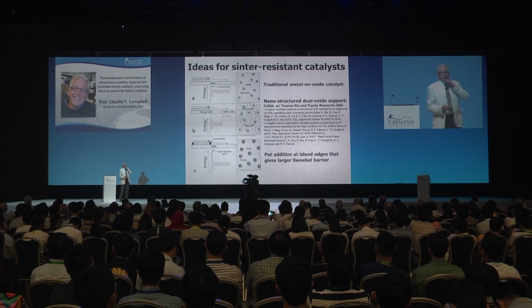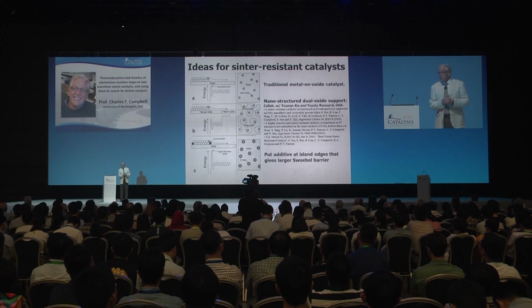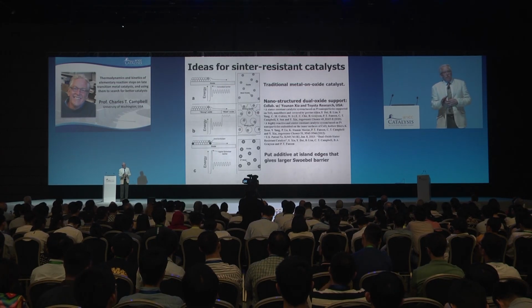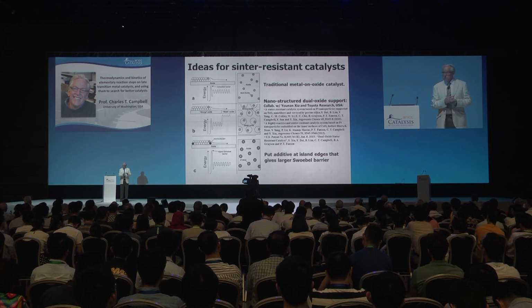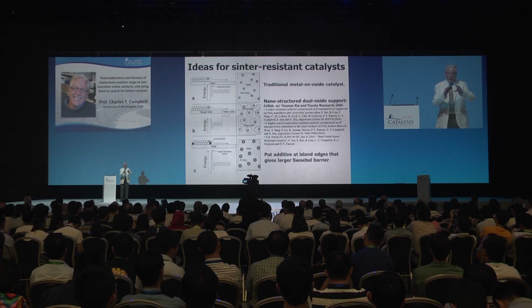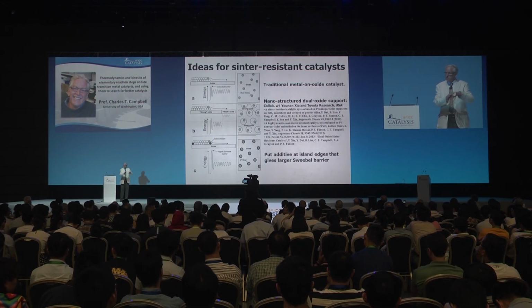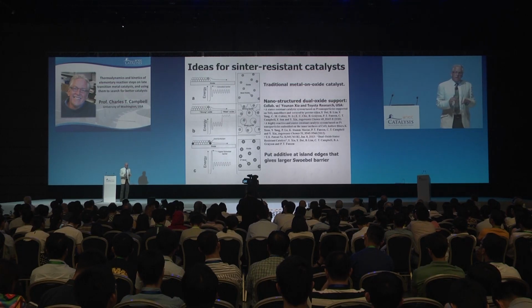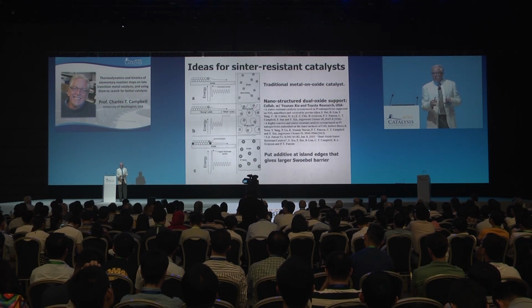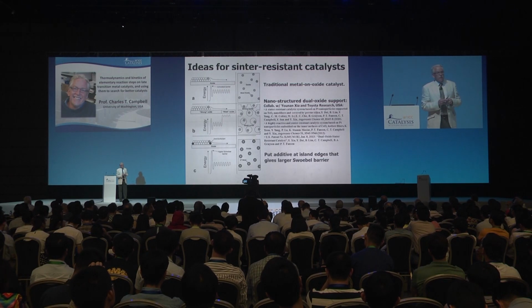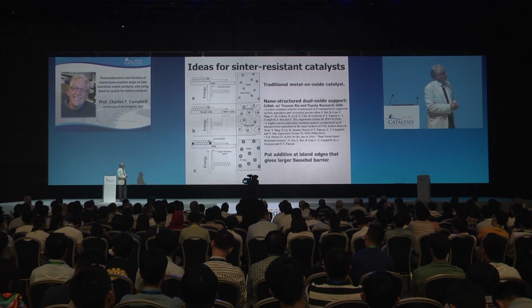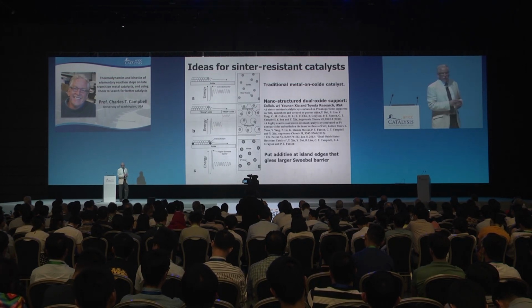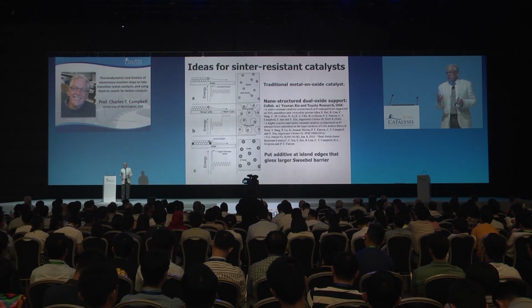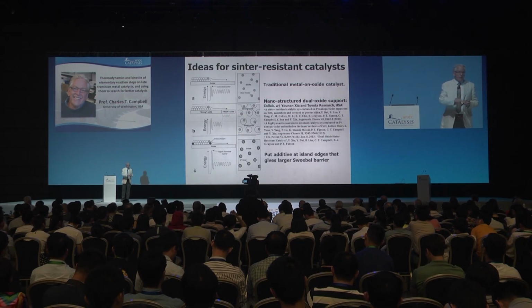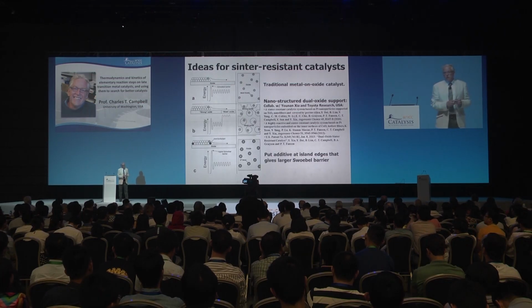Wayne Goodman first showed that by depositing titania on a silica surface in the presence of oxygen, it grew TiO2 islands on silica, and then he evaporated gold onto that and looked at the sintering of that with scanning tunneling microscopy and found that that kind of a structure sintered much more slowly than either gold on TiO2 alone or gold on silica alone.